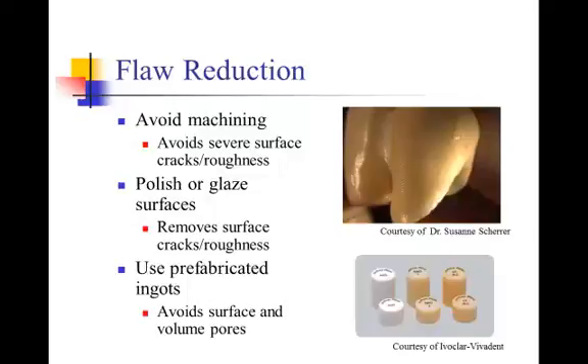One is to avoid machining or cutting the ceramic into the shape that you want, because this could lead to a surface that's very rough or has lots of cracks in the surface. For example, in this dental framework, you can see under transillumination a subsurface crack that has been induced in the material by the machine that milled it into the shape it has.